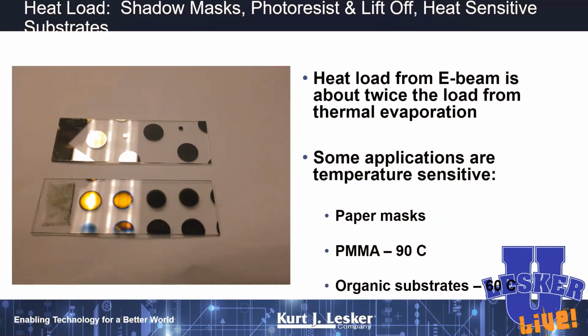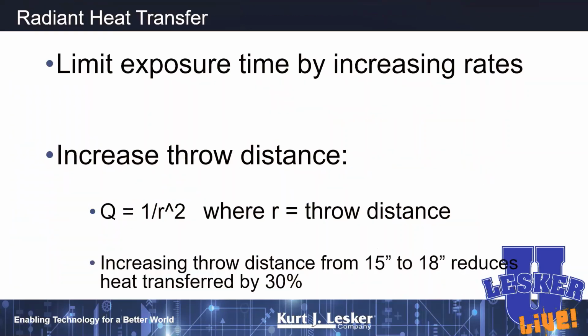Again, heating with E-beam is really, really tricky. So if you're using a paper mask, you've got to be careful. If you're trying to use PMMA, which may have an upper heating temperature of 90 C, or organic substrates, again, be really, really mindful with E-beam. Now, there's some things we can do, like increase the throw distance. If you've got enough head height in your E-beam system, maybe you can increase the distance between the source and your substrate. In this case, if you can add 3 inches to that throw distance, you can drop the heat transfer load by maybe 30% or so. Again, there's a couple tricks you can do if you've got a heating issue.